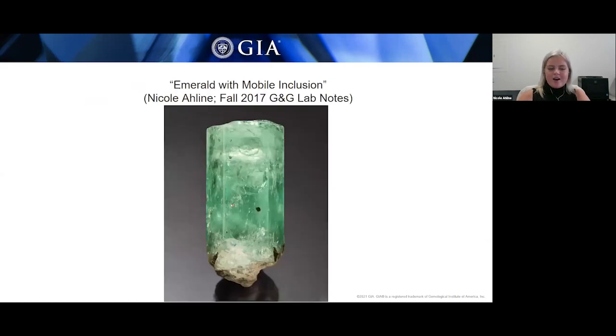So this rough emerald weighed about 9 grams, and it was sent to the Carlsbad laboratory for examination by Lucas Fazzari. When examining emeralds for origin, multi-phase inclusions are key indicators for origin determination, and typically require higher magnification and more maneuvering of the stone to get a more precise view. This emerald rough, identified using standard gemological properties, had an eye-visible mobile inclusion consisting of a CO2 gas bubble and a salt crystal suspended in fluid.